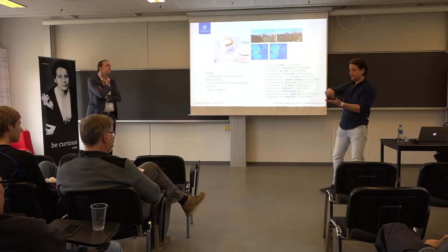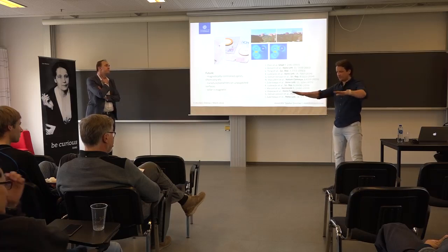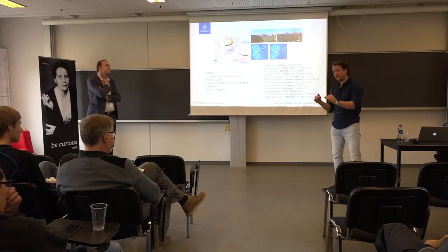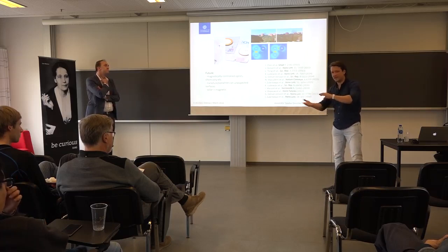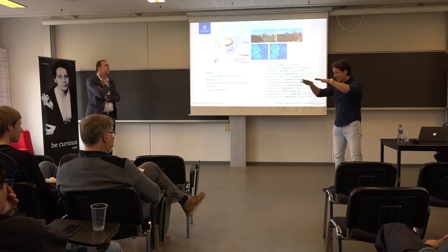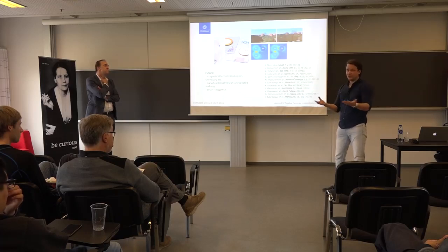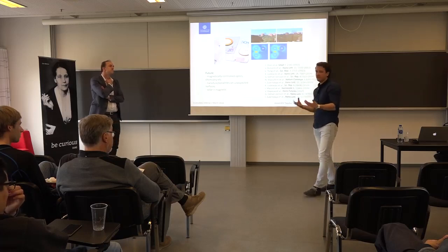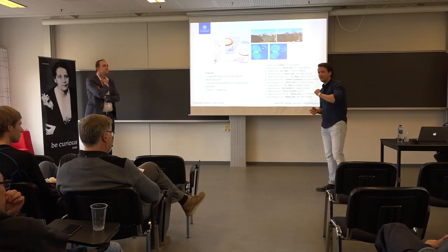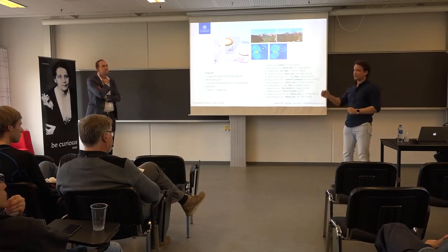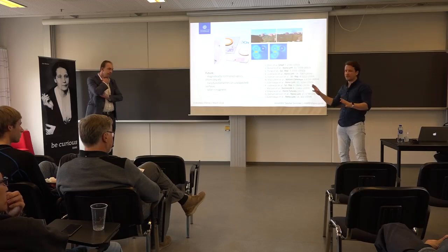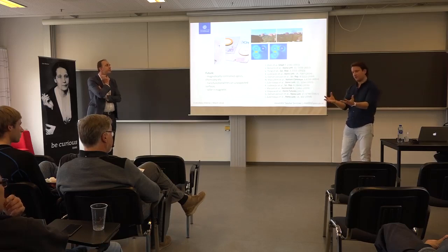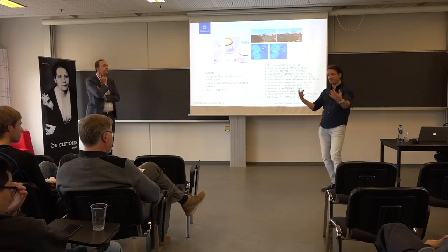You make your structures on the amorphous carbon film, and under that carbon there is some area that could be removed by, let's say, etching. Thus they start floating. But the carbon film is easily removed by a really brief oxygen plasma etch. It's enough to etch for 5 seconds, and the supporting carbon film is completely gone, even under the structure.